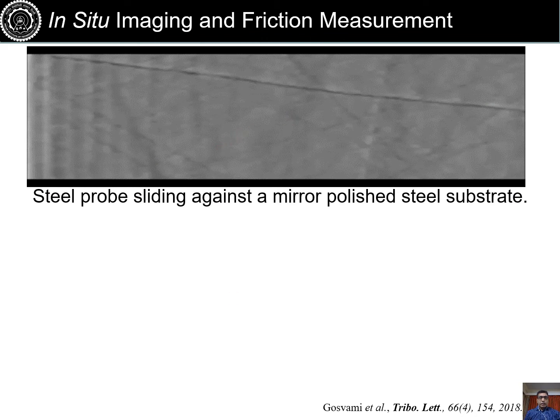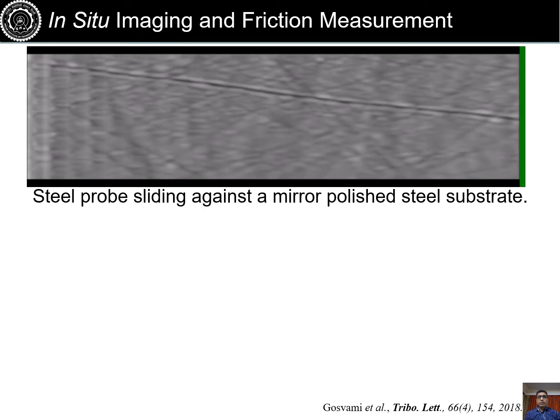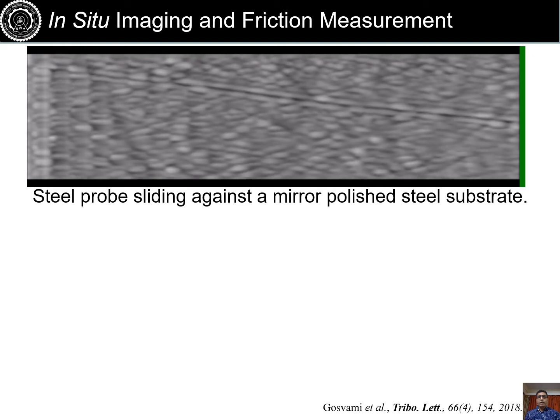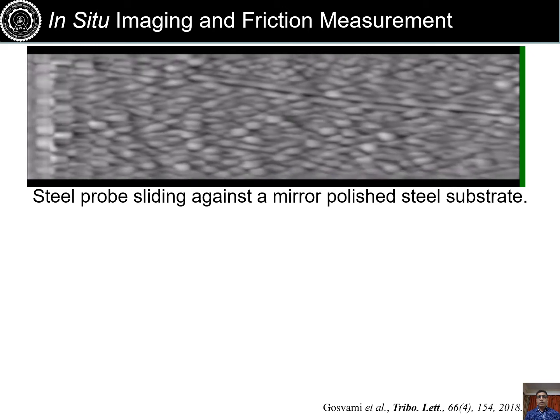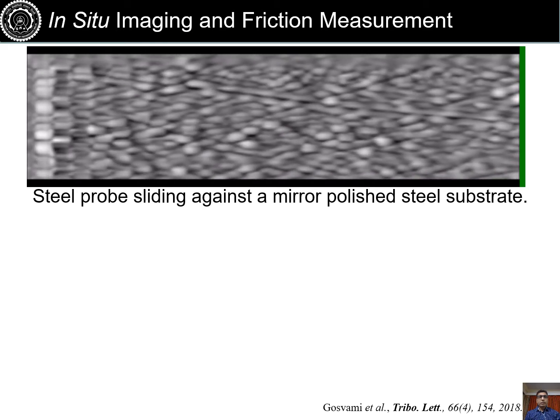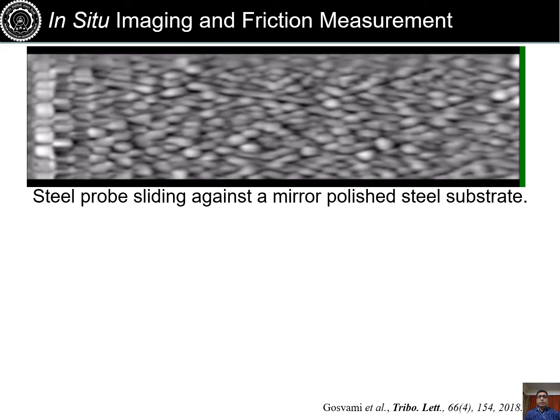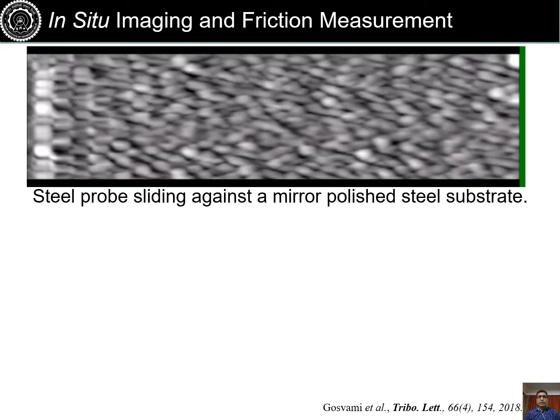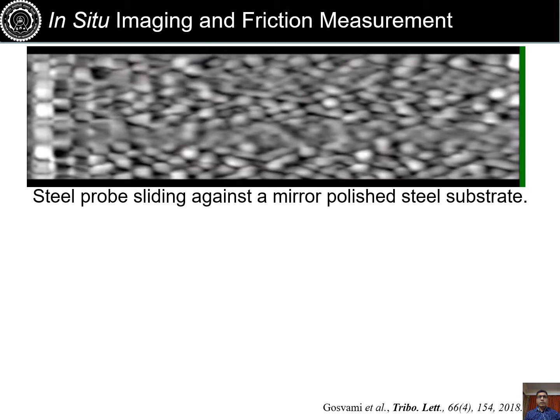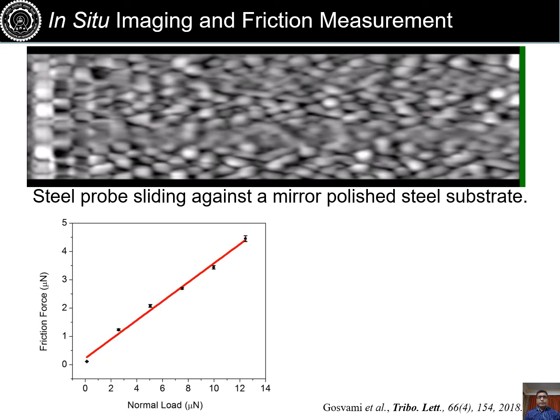So we found that actually when we did sliding, we could again simultaneously record the image of the sliding interface, and this is a polished surface. You can see the polishing marks, and you can see that film is growing, of course, preferentially on the sharp scratch on the surface because there are stress concentrations, and film is growing uniformly. It forms island like patchy topography, which we have seen previously as well in single asperity experiment. And we found that similar to the single asperity experiment, this film has formed only at elevated temperatures.